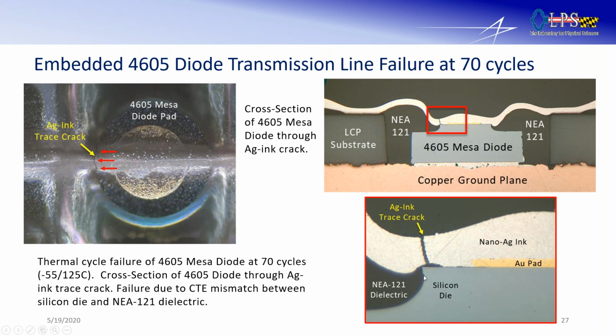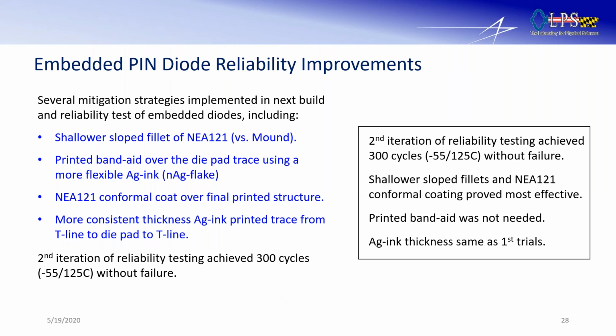We did a lot of analysis, did some modeling, and basically the CTE mismatch and the stress riser created by the geometry was causing a high stress area there, and it was causing a fatigue crack that failed at 70 cycles. In this case, we were cycling from -55 to 125, which when we do life testing, is more of our standard cycle. So 70 cycles obviously wasn't good enough. Our target was 300 cycles.